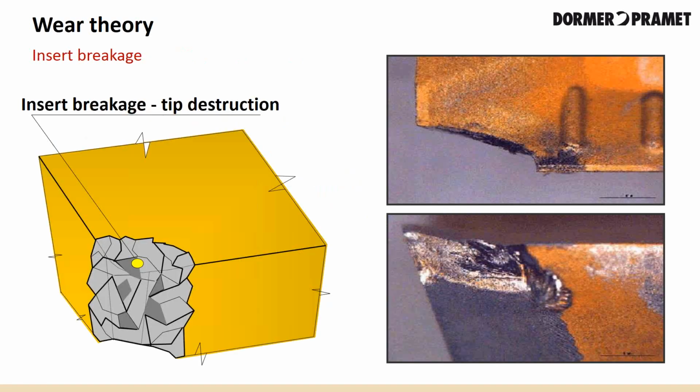Cutting edge destruction, caused normally by exceeding the power limit or limit conditions of the tool. Brittle fracture of the tool tip. This will more than likely occur in only 3 cases: when you're entering the cut, when you're exiting the cut, or when you cross some inequality or inclusion in the machine material.